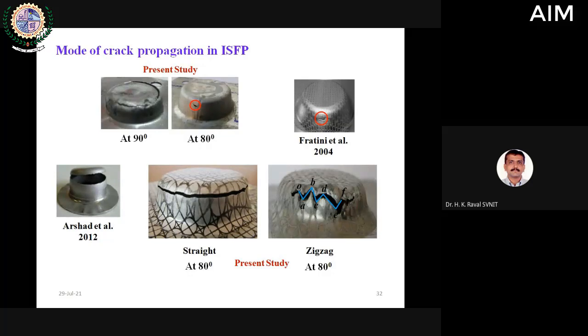failure in the straight failure as well as zigzag failure, just to correlate with similar findings in the literature. You can see failure can be of straight failure. There is a study done in 2012, and that is in similar agreement. Similarly, zigzag failure is also achieved in our case, which is comparable to other research done in 2004. So that is just to highlight the different types of failures.